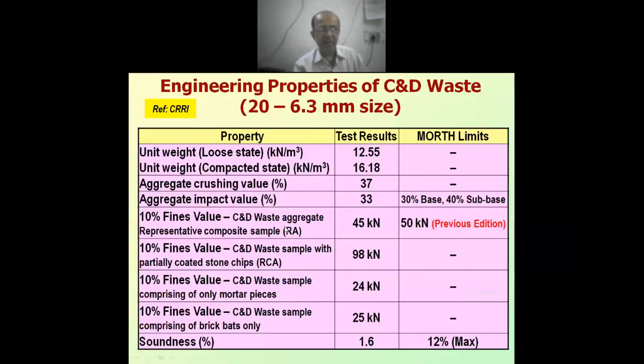So you can see that the composite sample, which is having all types of material, is a little bit less than 50 kilonewton. So it doesn't satisfy the 10% fines value. Whereas the stone chips, that is an RCA material, easily satisfy the 10% fines value. And then soundness is 1.6%, whereas the maximum limit is 12% as per IS 383.